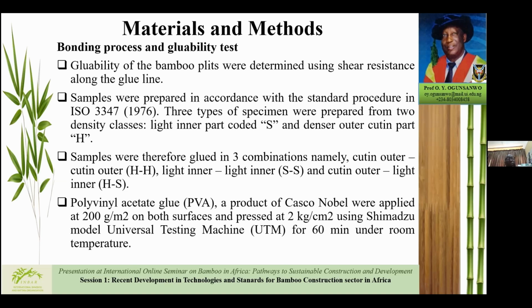Gluability test was done by putting the bamboo strips in the machine for shear resistance along the glue line. Samples were prepared in accordance with the standard procedure. In doing this, 3 types of specimen were produced from 2 density classes: the lighter inner part, which is coded as S, and then the denser outer part, which is coded as H. Samples were therefore glued in 3 combinations. That is, we have HH, that is outer culm and outer culm. Then we also have SS, that is lighter inner culm and inner culm. And then you have SH or HS, which is outer culm and inner culm.